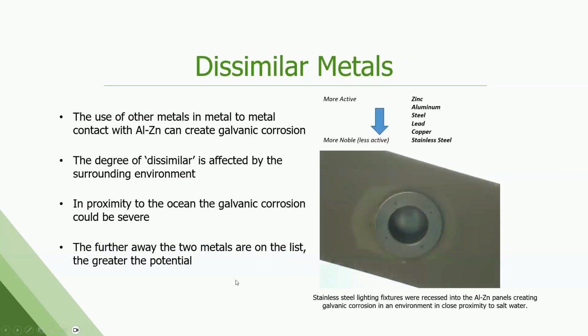Dissimilar metal is a big one. I know we're running tight on time, so sorry, I'm going to go really fast. This is really an issue around marine settings. So if you're in a corrosive environment near salt water, the biggest ones we see is stainless. Stainless is not compatible with hot dip galvanized or galvalume product next to the ocean. The galvalume or the galvanized is going to sacrifice itself for the stainless steel component. And what it does is it actually corrodes underneath the paint. So the first indication that something's going on is your paint is bubbling and lifting.